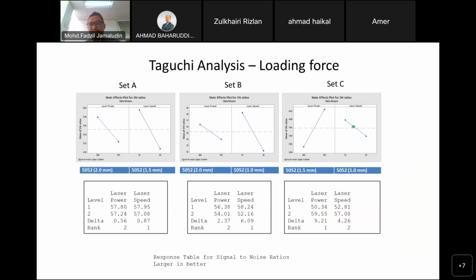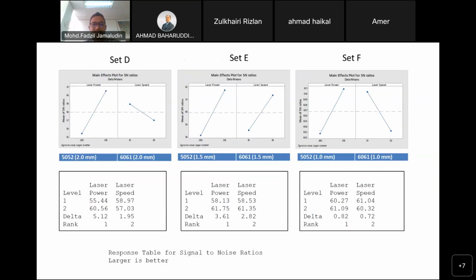So from the Taguchi analysis, we can see that the most significant factors are laser speed and laser power, and laser power is more significant than the laser speed. In terms of ranking, laser power is ranked higher. It has a higher influence on the tensile strength.